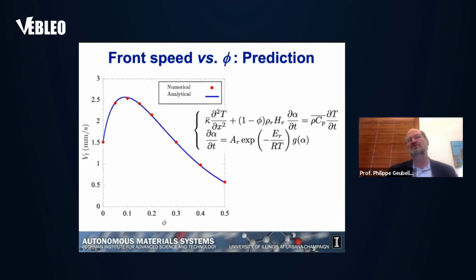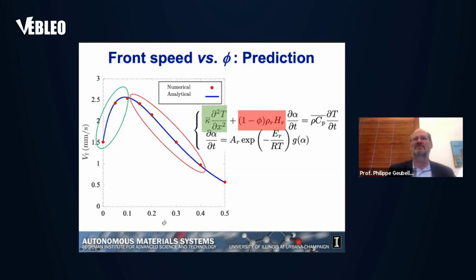And this can be explained by just looking at the 2 equations that I just showed before. You can see that the increase is associated with the fact that the homogenized thermal conductivity of the composite is higher due to the fact that the carbon fibers are more conductive than the matrix. On the other hand, as you further increase the fiber volume fraction, we start to see a decay, and that's really associated with the fact that the source of heat that shows up in the second term over here has this 1 minus phi term in there, indicating that the more fibers you have, the less resin you have, and therefore the less source for this exothermic reaction.